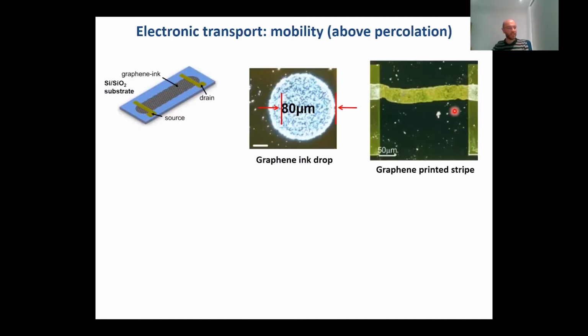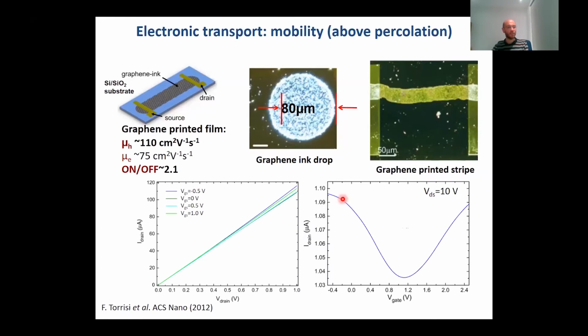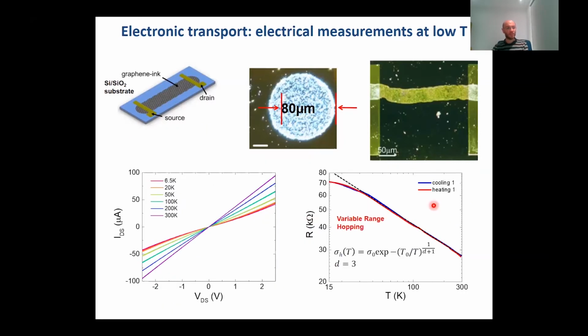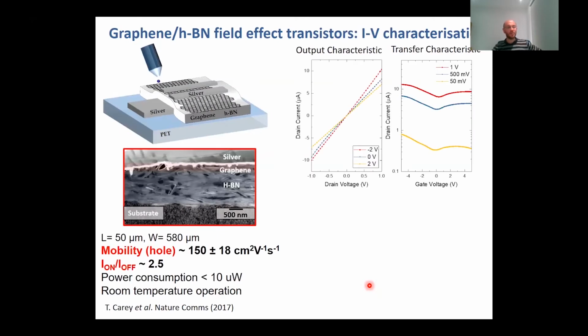We can get very nice devices. We can look at the mobility of graphene transistors, and you can see it's very high here. And also we can look at the transport. In this case, it's a three-dimensional behavior. I'm trying to go quickly. But particularly, this enabled us to print transistors. And in this case, these are fully printed devices using graphene and boron nitride, here with a mobility of up to 150 centimeters square per volt per second.